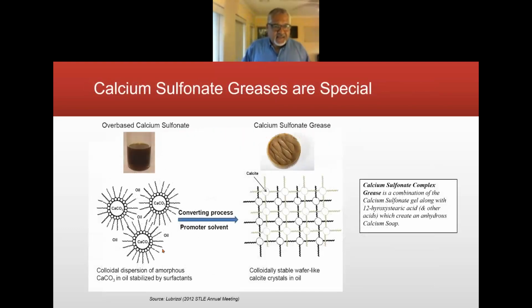A similar structure applies when we speak of over-base calcium sulfonate. This is before it's complexed to make a strong calcium sulfonate grease. Included in the micelles are the calcium carbonate particles. This is where you get your wear protection from, the calcite particles here. And you have the oil still trapped by the oil soluble tails here. In the converting process, once we include a promoter solvent, here's the grid structure that complexes the grease and makes it a usable thickener.